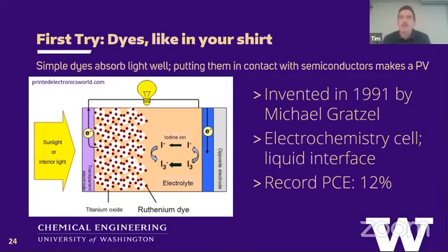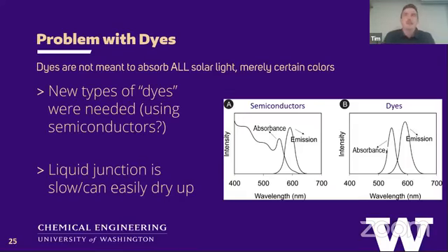For reference, a silicon-based panel in the field today has about 20 to 25% efficiency, and the thermodynamic limit above which no solar cell by itself will ever achieve is 34%. And so, 12% isn't too bad because 34% is your maximum, but it's still not good enough to compete with silicon. But this was more important than just the dye itself, because it gave chemists and material scientists, a whole new class of researchers, the idea that they could contribute and make new types of solar cells and solar panels. And so the next idea was to tackle two birds with one stone.